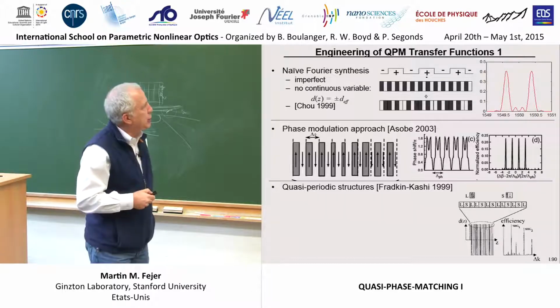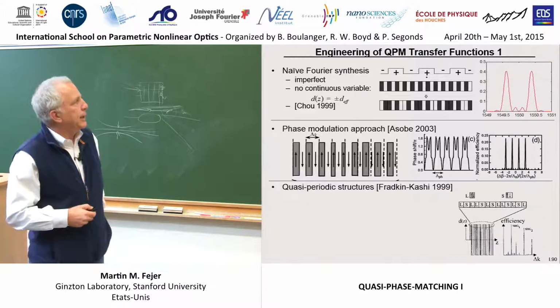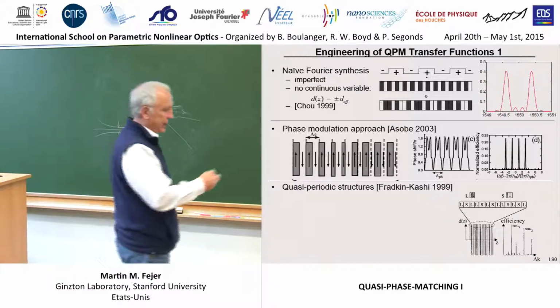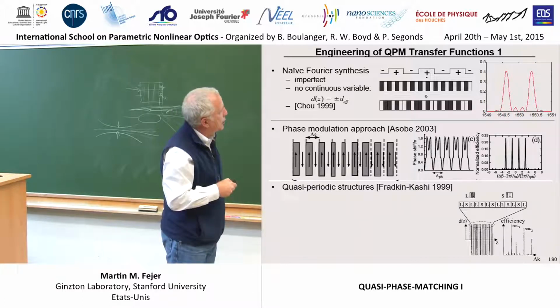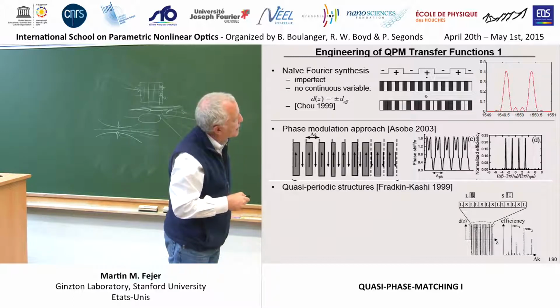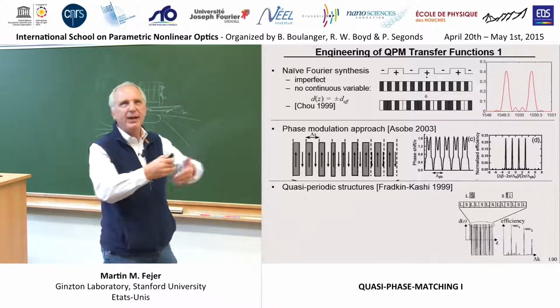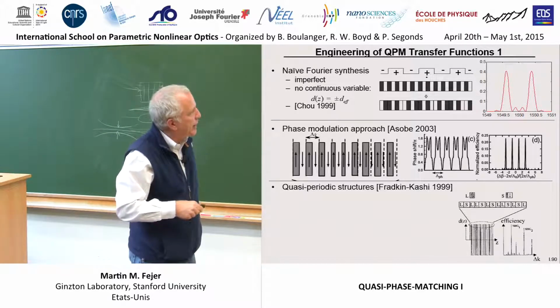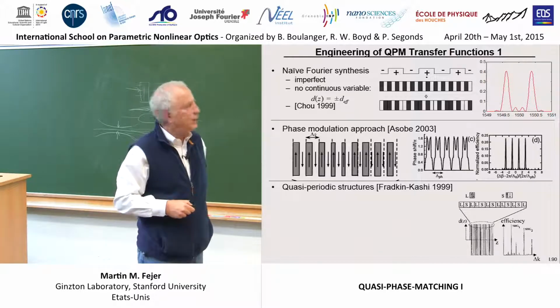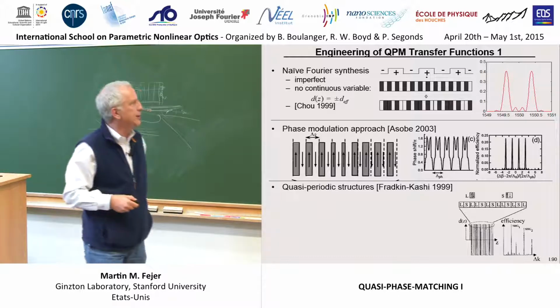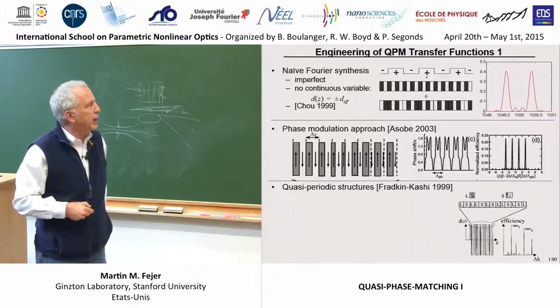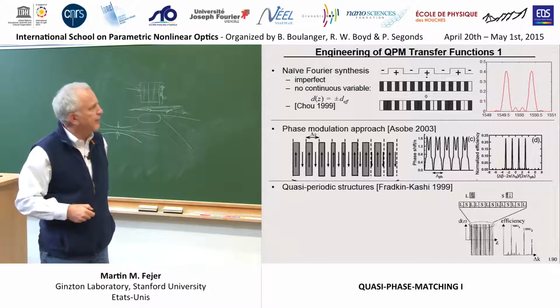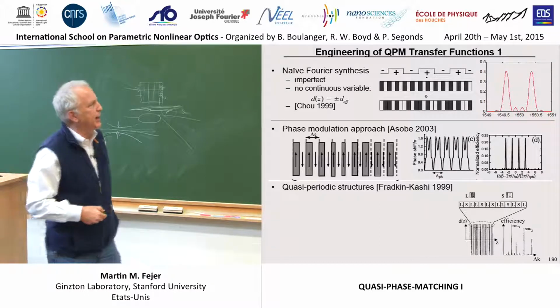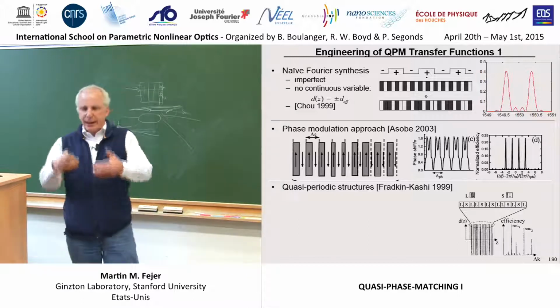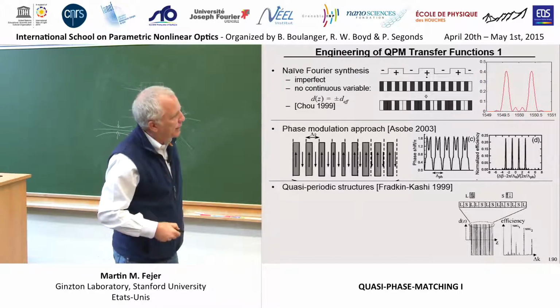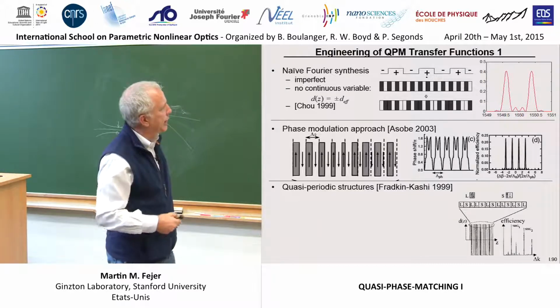What turns out to be a better approach was from Asobe at NTT. Instead of doing this kind of product of Fourier components, he did a phase-modulated grating. So he took this grating, and then he slowly moved the edge away from its nominal position, and then he slowly moved it back. So it looks like phase rather than amplitude modulation. This is the particular phase modulation function he chose to accomplish a 4-peak curve. And you can see that he ends up with fewer side lobes than we did in our case. Perhaps Adi Arie, when he comes here next week or later this week, he did some work on so-called quasi-periodic structures, things akin to Fibonacci sequences and the like. And by using quasi-periodic building blocks, you could generate some complicated patterns, though I think this probably never ended up being as good as that.